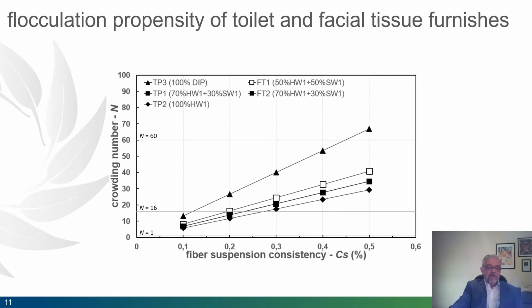Here we have the results of flocculation propensity of toilet and facial tissue furnishes. It's clear the adverse effect of softwood content on the flocculation tendency. Toilet paper based on 100% hardwood has a lower crowding number of about 15% than that blended furnish made of 70% hardwood and 30% softwood. The same effect is observed for facial tissues when softwood mass fraction in the furnish is increased from 30% to 50%.